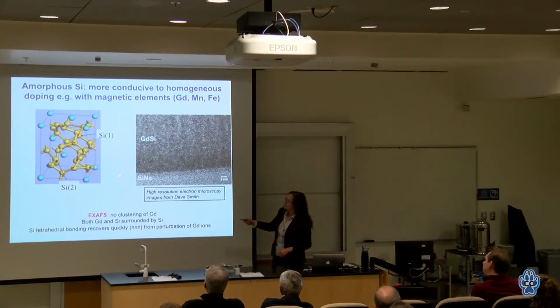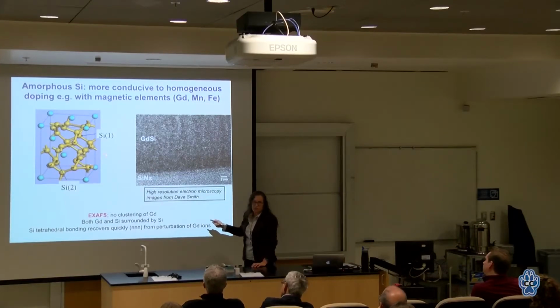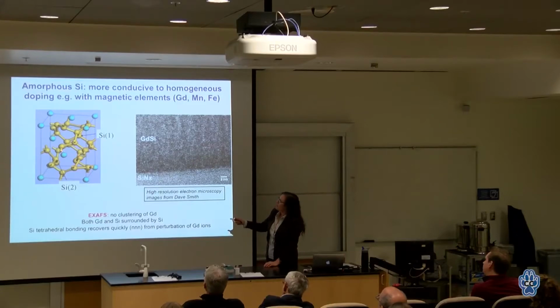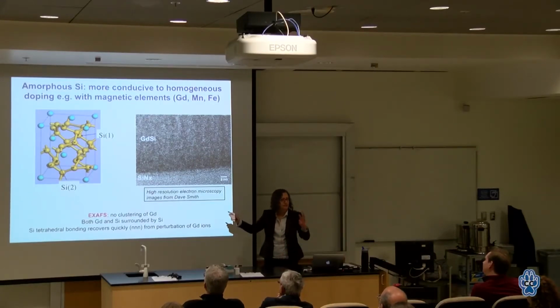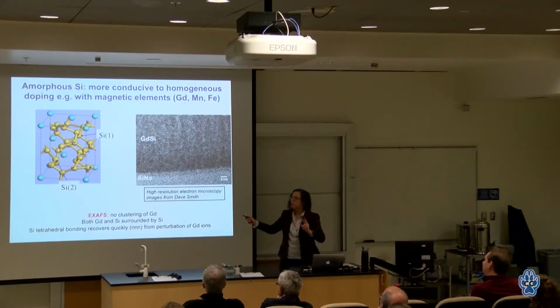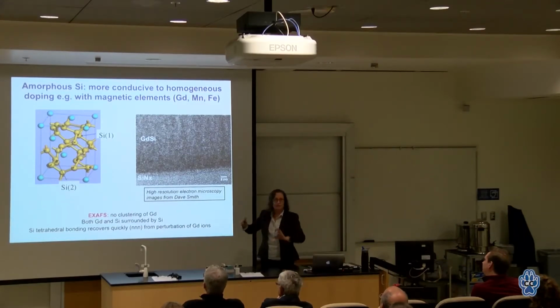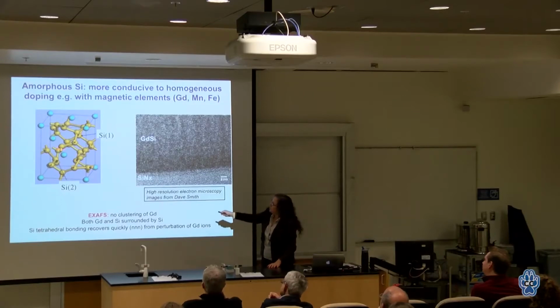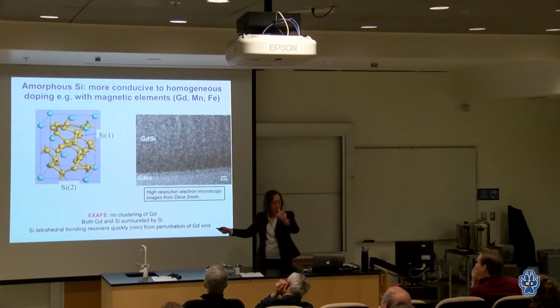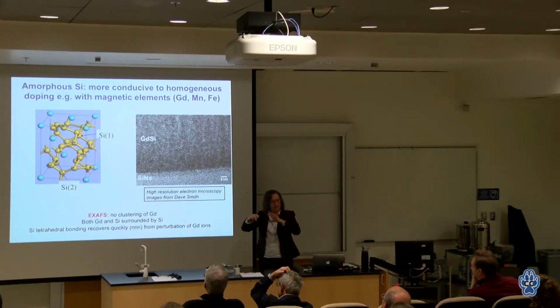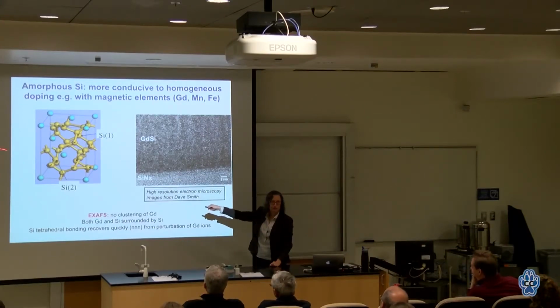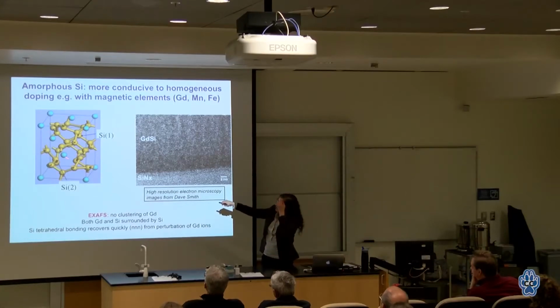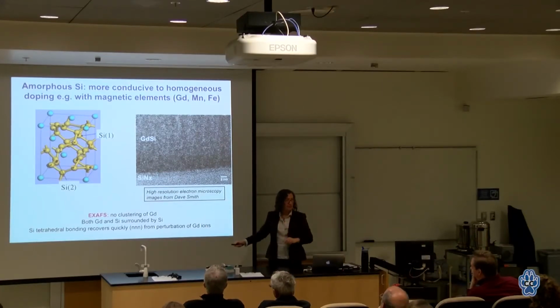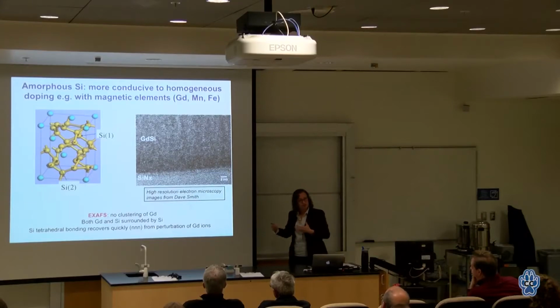But the amorphous structure, so this is a schematic done by a theoretical colleague of mine. The blue are the gadoliniums, and if you look at just the yellows, you'll see the same tetrahedral bonds that I showed you before. But around the gadoliniums, they make these funny little cages. If you look in detail, every one of the silicons in this funny little cage is still tetrahedrally bonded, but they're kind of flattened, and so they end up with this cage-like structure around each gadolinium. But one atom away, they're back to their nice tetrahedral bonds. So the amorphous structure is very forgiving.